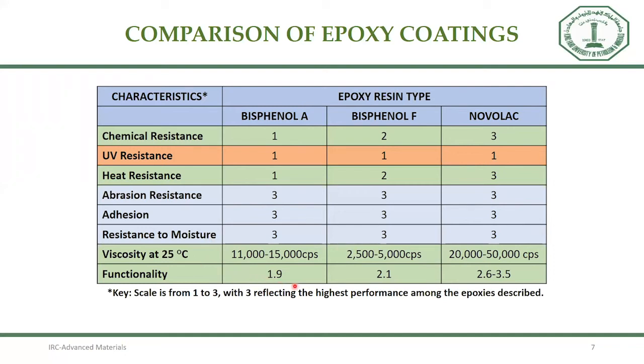And when you consider the viscosity, depending on the viscous nature, we can select. For example, when we need low viscosity, we can go for bisphenol F. When we need a high viscosity material, we can go for Novolac epoxy. And another small issue when selecting epoxy coatings is that they have less UV resistance, because whenever we expose an epoxy coating to atmospheric conditions, because of the sun radiation, it can undergo some photo degradation. So it causes UV degradation of the polymeric matrix.